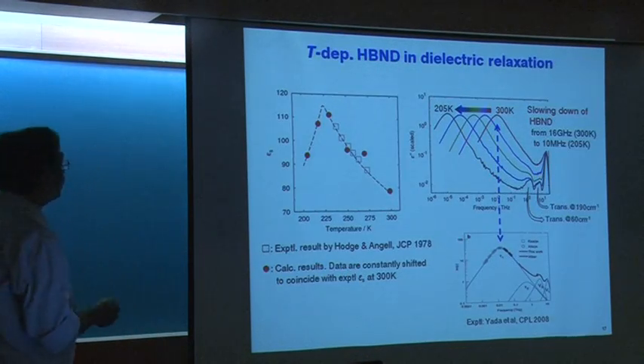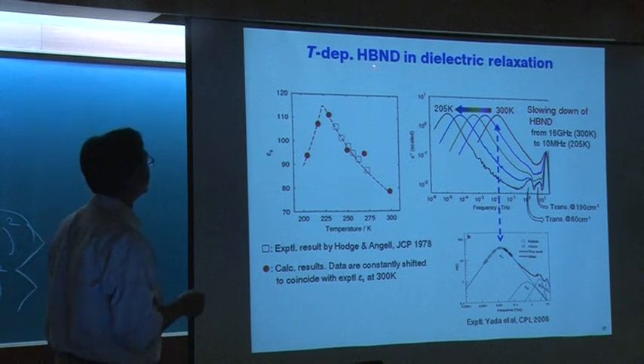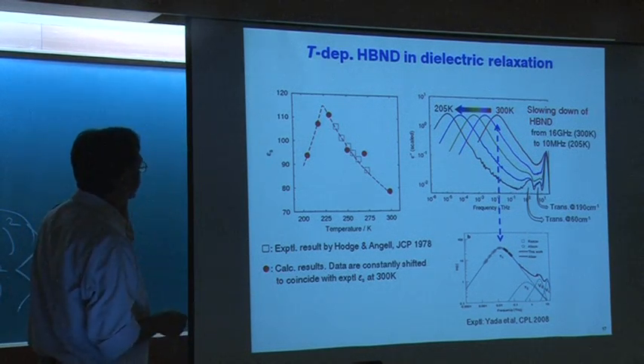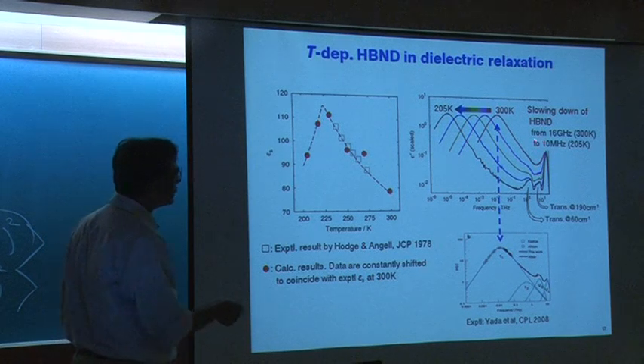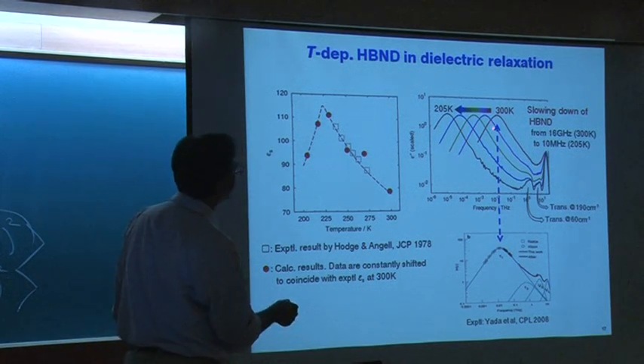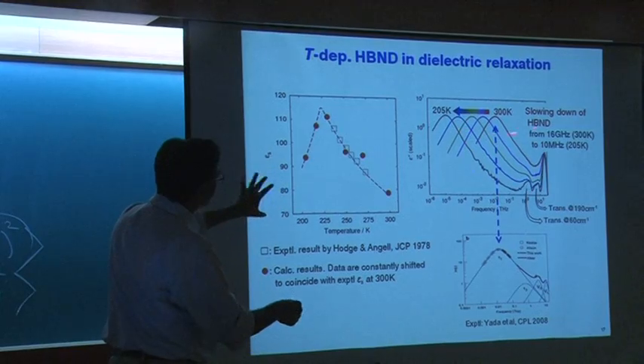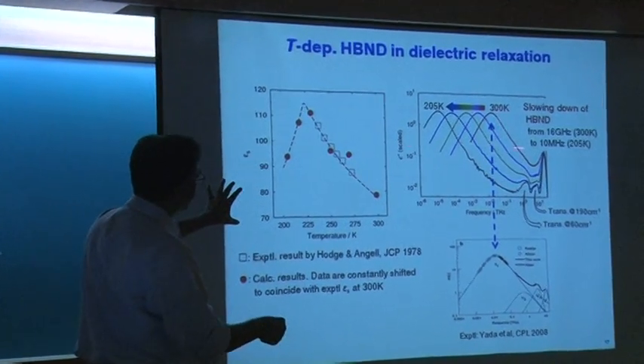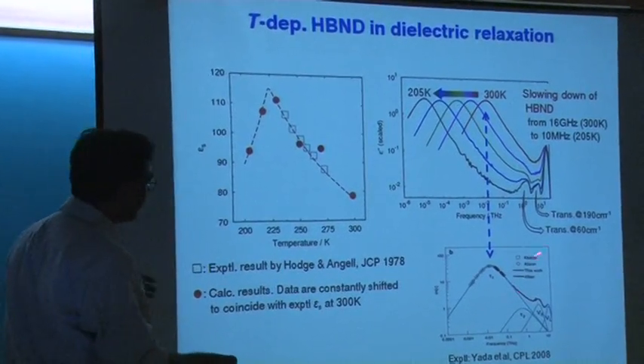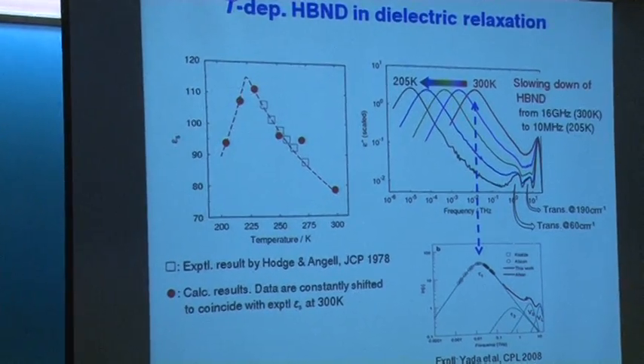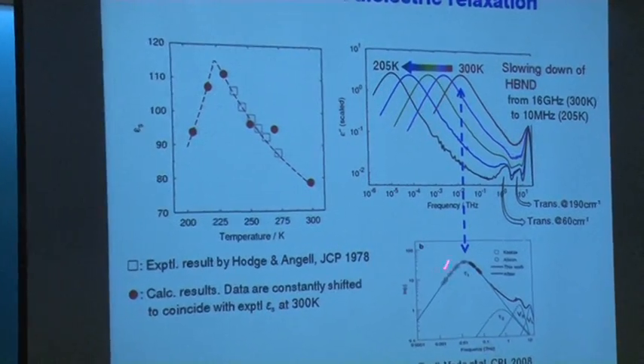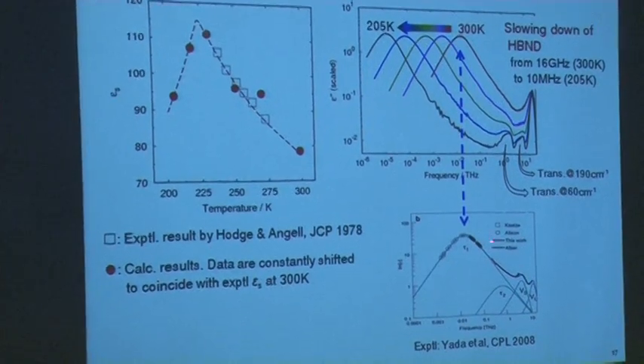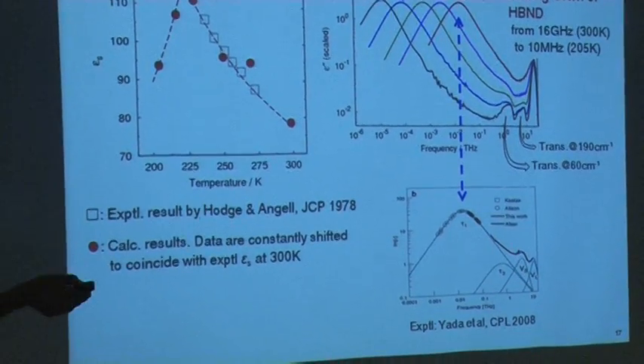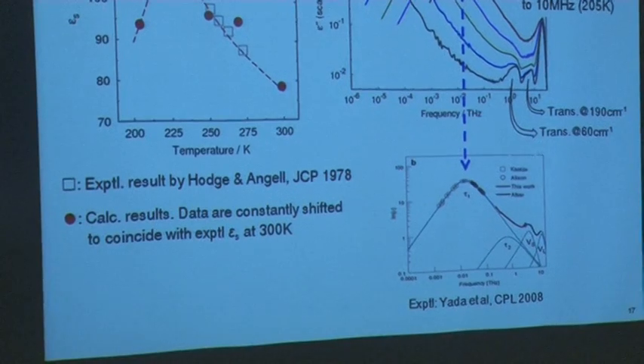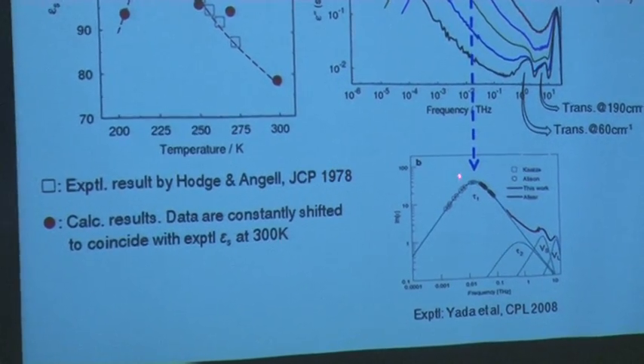There is one more thing here: we got the frequency dependent dielectric relaxation. That again shows very much like frequency dependent specificity, the emergence of slow dynamics, much slower than at high temperature, and that agrees quite well with the experimental results. This one is 300 Kelvin and these are the experimental 300 Kelvin. We have compared our data with the experiment, and you can see you cannot go below a certain temperature here.